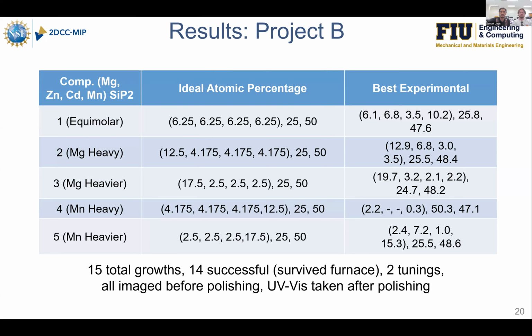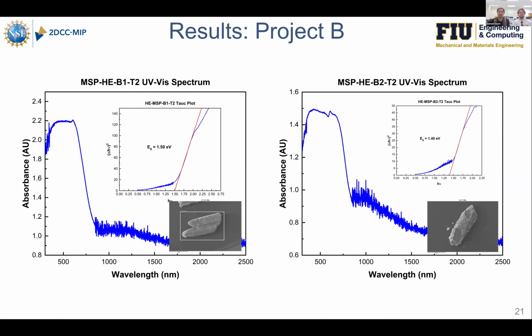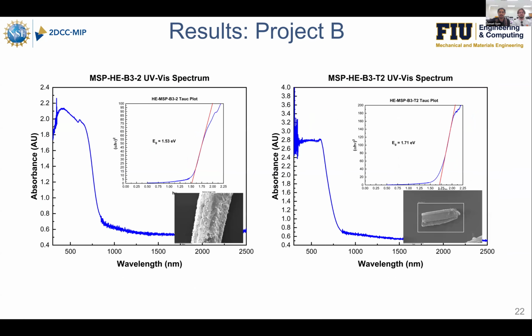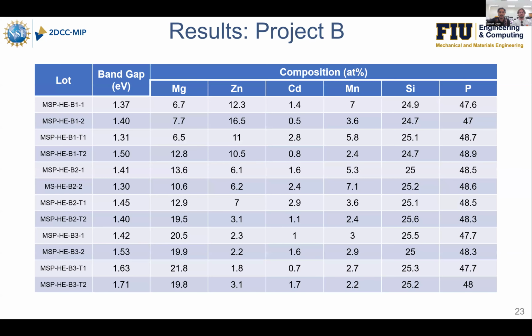Moving on to the UV-vis for these as well, we see the insets of the pre-polished crystals, we have absorbance in the visible spectra, and the band gaps that we were able to get from the UV-vis were anywhere between, we don't have the images here, but some of them were as low as 1.37 if I'm not mistaken, all the way up to about 1.71. And here we have the EDS taken after polishing as well.